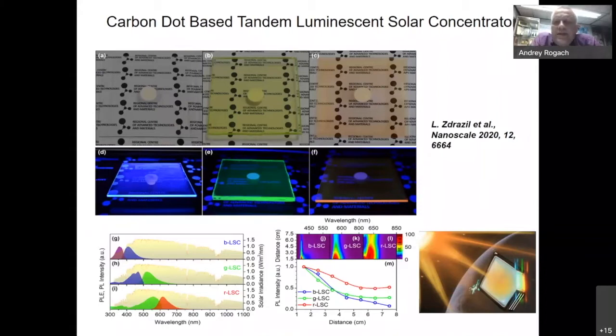So another very recent example of the use of carbon dots, which emit light in different colors, will be to use them for this so-called carbon dot-based tandem luminescent solar concentrator. This is a device which is essentially a few layers of coating on top of glass. And when we illuminate them by sunlight, these carbon dots will emit light depending on their size, for example. So this light can be blue or green or red, or a combination of all of these lights when we put them on top of each other. And this light will be mostly coming out from the edge of this glass.